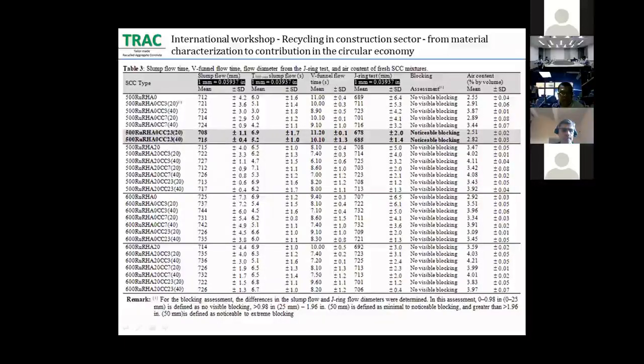The results show that calcium carbonate has an effect on the flow through the J-ring, similar to the initial slump flow, by increasing the J-ring flow both with and without rice husk ash. For self-compacting concrete containing rice husk ash, calcium carbonate also improves flow by decreasing high viscosity to low, due to the water absorption of rice husk ash, which causes densification of the self-compacting mixture and difficulty in changing the shape of flow under the gravitational force of the mix.